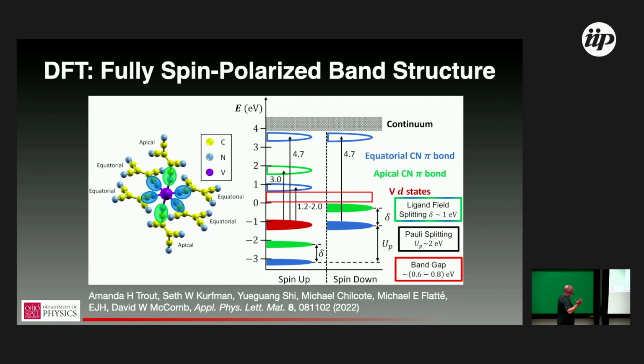That being said, this model and this understanding can tell us a lot about the material's properties. Working with Michael's group and David McComb at Ohio State, who's a TEM microscopist doing electron energy loss studies, we were able to develop this picture of what the electronic structure actually looks like. And what we discovered is that not all TCNEs are created equal. There are 4 in-plane equatorial TCNEs, and then 2 apical, sort of vertically stacking TCNEs.